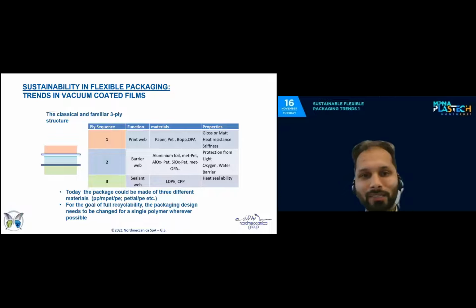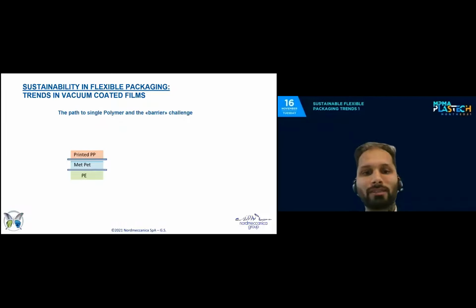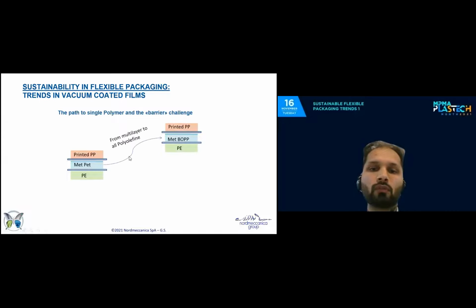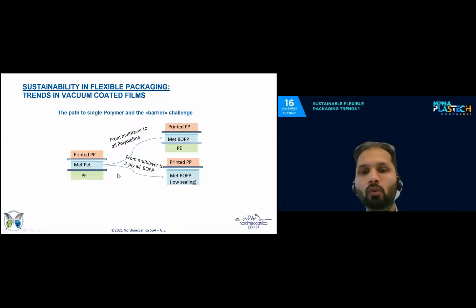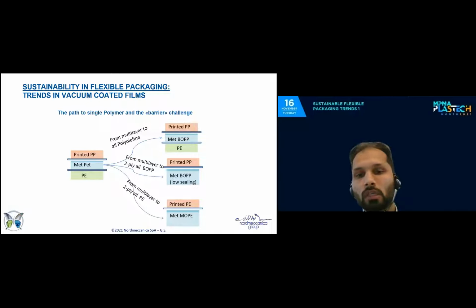We need to redesign the conventional three-ply into single polymer structures. And how can this be done? For example, we have the printed polypropylene, metallized polyester, and polyethylene. So from the multi-layer, we can go to our polyolefin structure. So we substitute the metallized polyester with the metallized BOPP. Or we can go from the multi-layer to all two-ply BOPP. Or we can even go from a multi-layer to an all polyethylene structure.